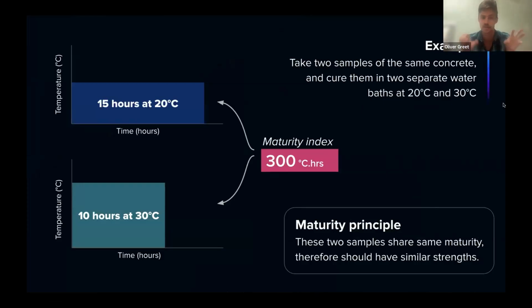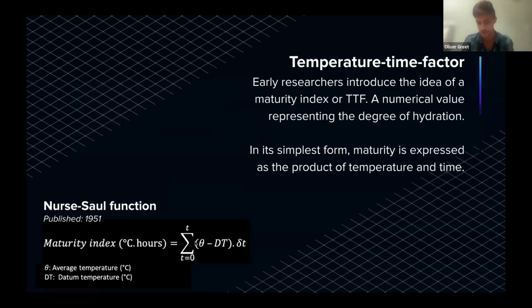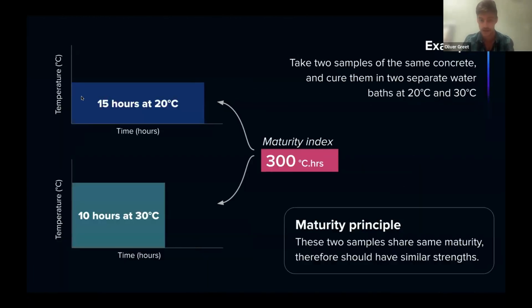In this case, we're going to take two samples of the same materials, same concrete mix design, cured in two different thermal environments. And the first function that's published is quite simple. It just takes the area underneath this chart, essentially, underneath each temperature profile. So in the top left case, you can see the sample curing for 15 hours at 20 degrees. And in a second case, we're going to cure a sample for 10 hours at 30 degrees. And what the researchers posited was that both of these samples have accumulated the same area underneath their temperature profiles. And as a result, they share the same maturity and notionally should have a similar value of strength.